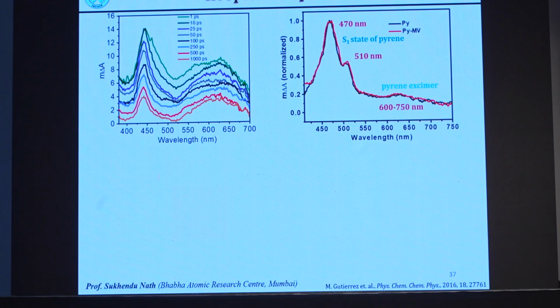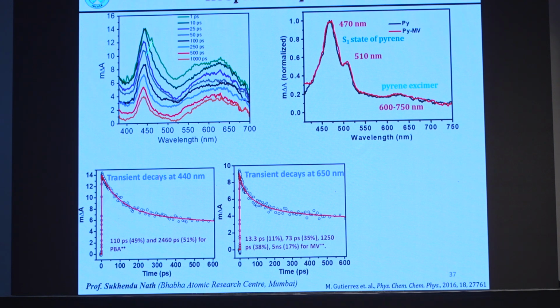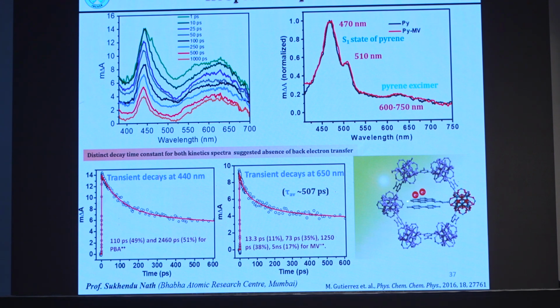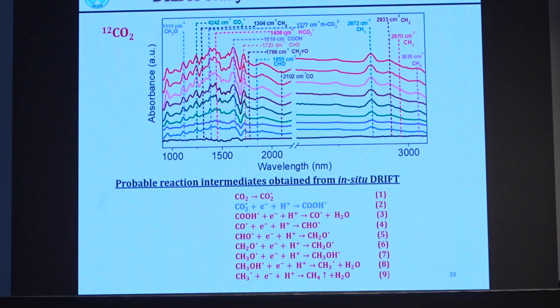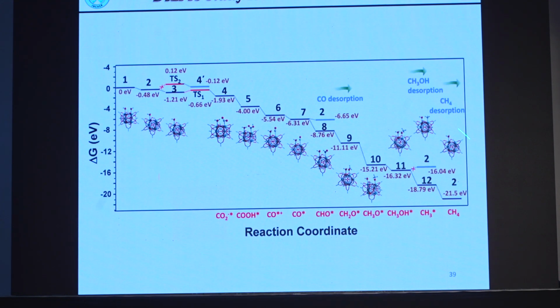Then further we try to do the transient absorption, okay? So transient absorption, what are we getting? This is the pyrene cation radical, and this is the methyl viologen radical. This is the excited state absorption band. When we analyze the decay at 440, you can see there is a different decay. This means a distinct decay time, showing the electron and hole are not simply recombining, and electrons can come from the donor to the acceptor, the methyl viologen. Okay. So then again we have tracked this whole process.